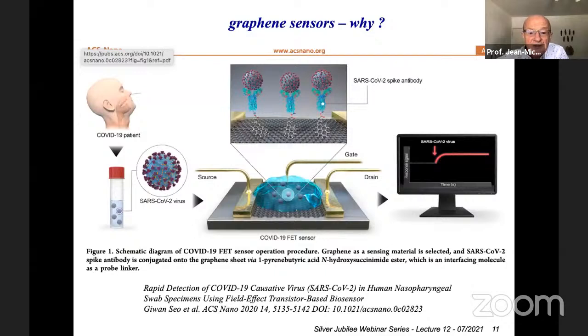I'm showing that paper because it was recently published, and they designed the graphene sensor with some ligands which were able to trap and detect the SARS protein, the spike. They had spike antibodies, and they were able to detect the presence of the spike antibody, which makes, by way of consequence, a SARS-CoV-2 COVID detector. So I'm showing this one because that was an interesting result.